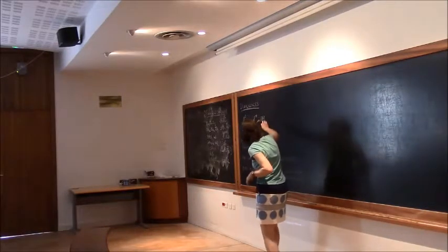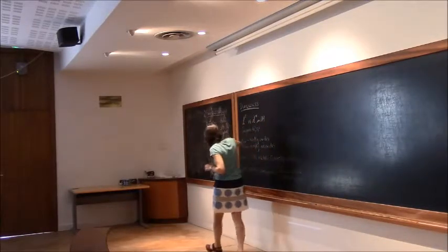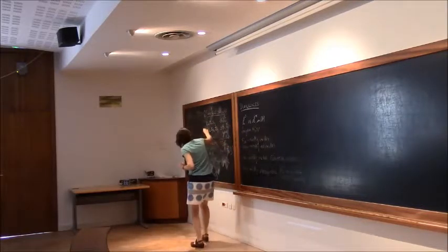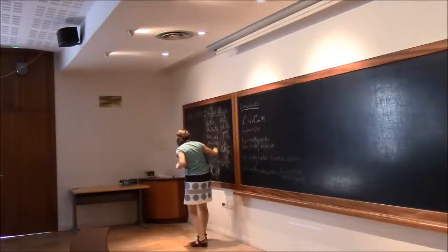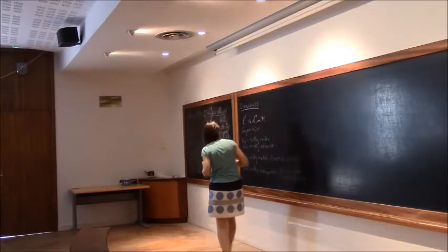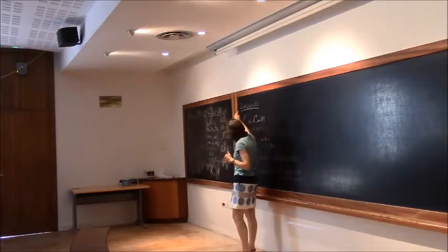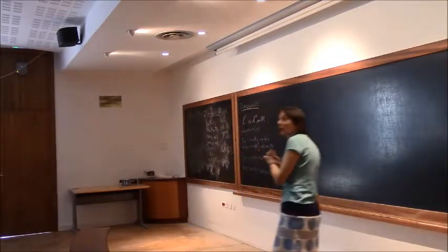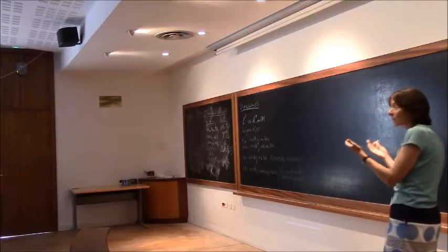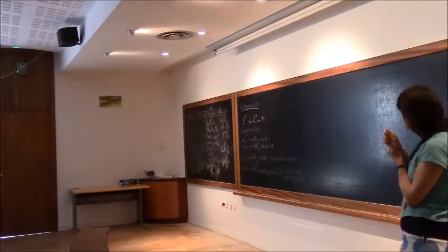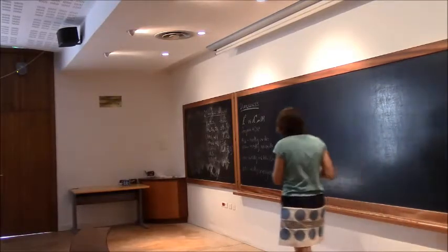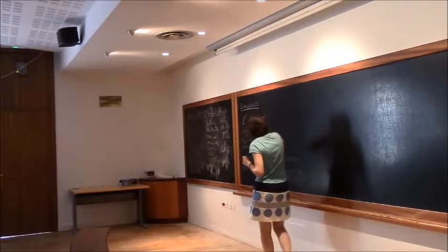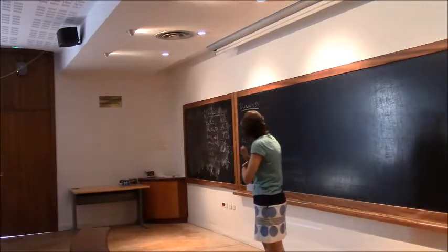One group was discussing, already wrote this up. If you look at all of your ferroelectrics, apart from the multiferroic ones, the ones where we solved the problem of making the magnetic and ferroelectric, the formal charge of the transition metal has empty d electrons. So for example, titanium 4+, there's no d electrons. Niobium 5+, there's no d electrons. Whereas to be magnetic, we need some source of localized electrons, which in a transition metal is the d electrons. And we'll talk about why that is.